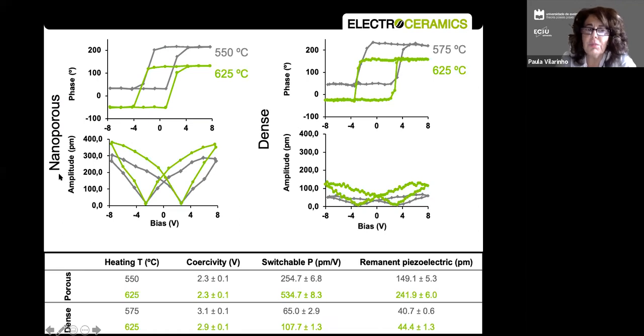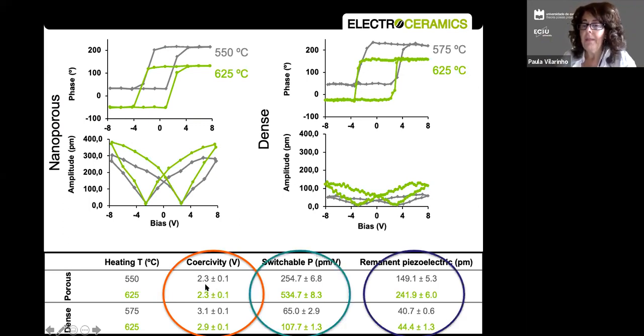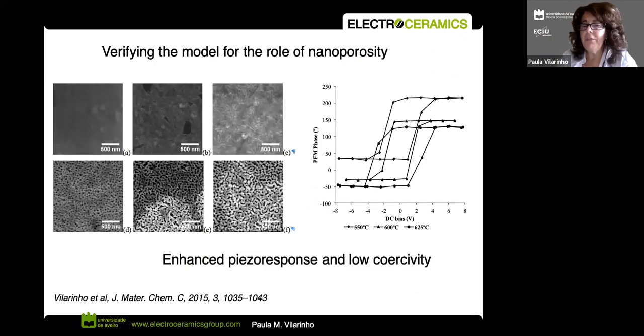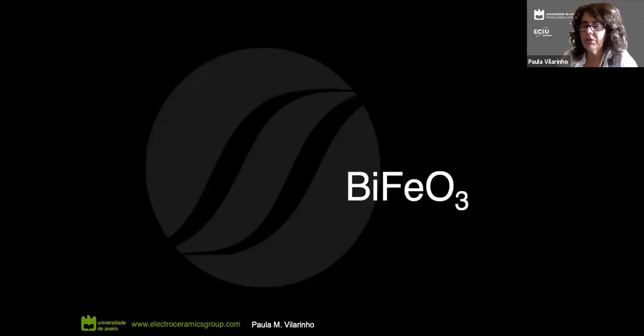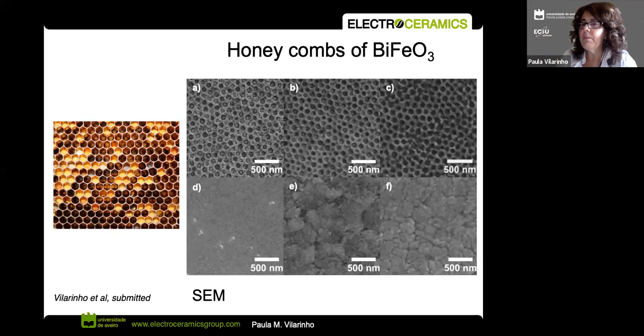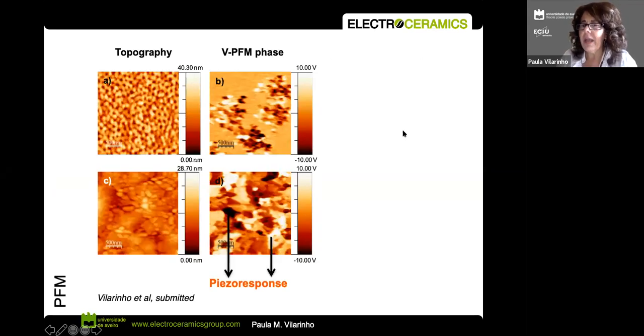So that's the response, again, from atomic force microscopy, because these things are so small that that's the tool that enables us. And as you can see here, the coercivity, that's something important, is the amount of electric field that I need to use to switch. So this means that the amount I have to use is smaller, and this gives us better properties for these local nano materials. We verified the model in terms of local materials, and we also verified the same phenomena for bismuth ferrite. So we decided to produce these nano honeycombs, very well organized, as you can see here, and try to see what is happening in terms of response.